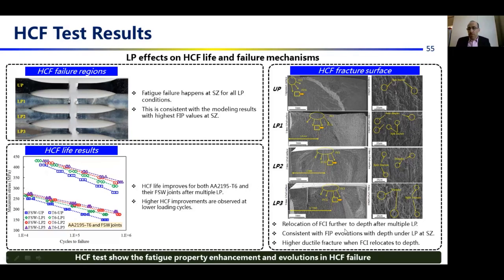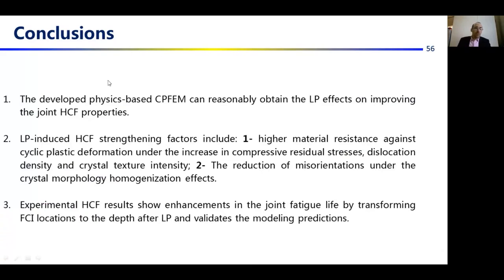And the relocation of FCI, which is the fatigue crack initiation location, further to the depth after laser peening validates the grain average FIP value results, and higher ductile fracture is also observed when FCI relocates to the depth, which shows the effects of relocation of fatigue cracks to the depth on improving the fatigue life. For overall conclusion, the developed physics-based CPFEM can reasonably obtain the laser peening effects on improving the